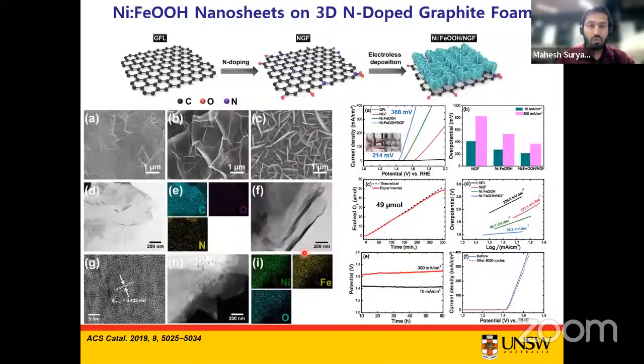In our next work, we also explored the role of Ni doping into the iron oxide hydroxide, as well as a different catalyst support, which is nitrogen doped graphite foam. With a similar approach, we observe that with nickel doping, there is a significant improvement in the overpotential value.